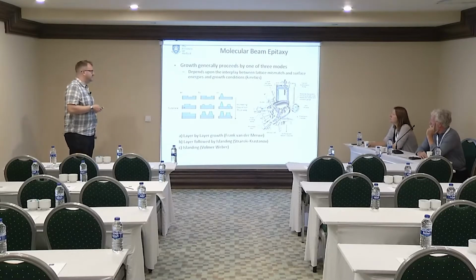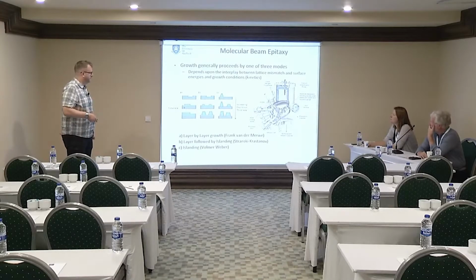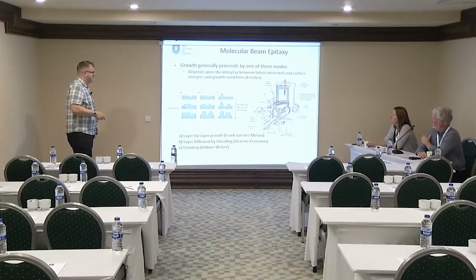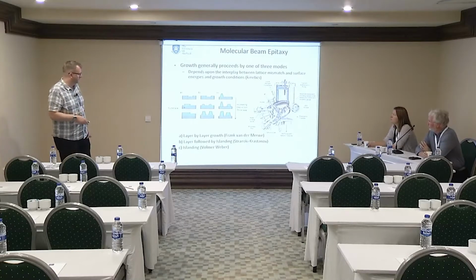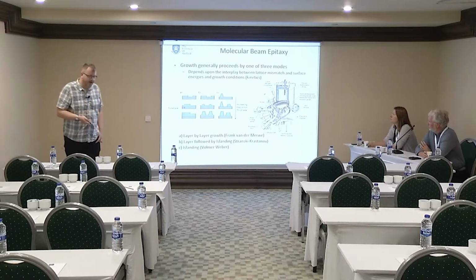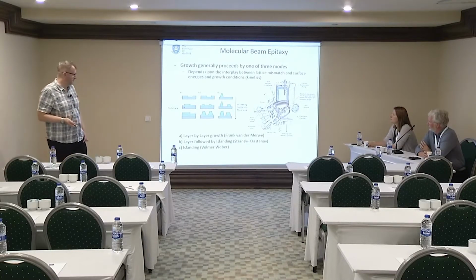Generally, unless we do something very strange with the substrate, growth proceeds by one of three modes. We either have a layer by layer type approach, we have just islanding, thinking of something like water on glass, or then we have an unusual mode in the middle where we get an initial layer followed by a relaxation of the strain by forming islands, known as the Stranski-Krastanov growth. And this is the method that we're using to form quantum dots.